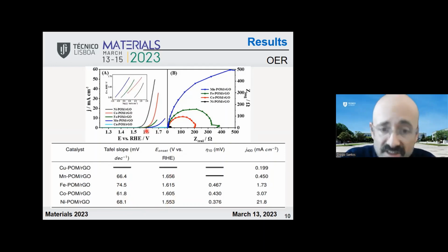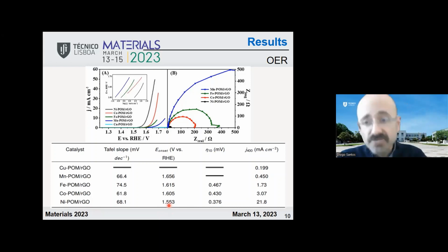In terms of onset potential, which means the potential from which the oxygen evolution reaction starts, we want that to be as low as possible to reduce our electric consumption. And we've seen that the nickel POM has the lowest onset potential for oxygen evolution reaction, which is very interesting. So this shows the best activity of the nickel POM, which is consistent with what we observed with